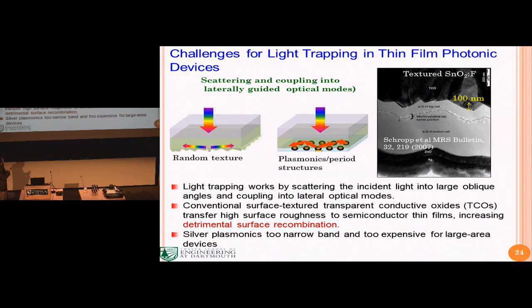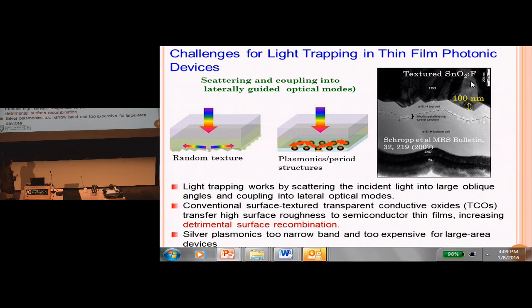The downside, though, is that you can see these traditional TCOs are very rough. When you have a rough surface and you deposit active materials, you increase the area of that interface. Interface is never perfect. The more interface area you have, the worse the electrical properties. So this is why there's a limit in that sense.